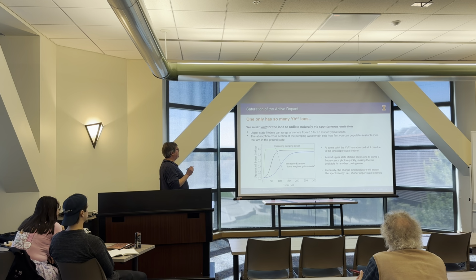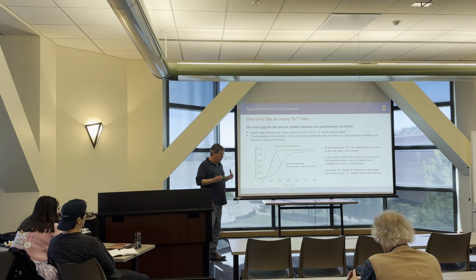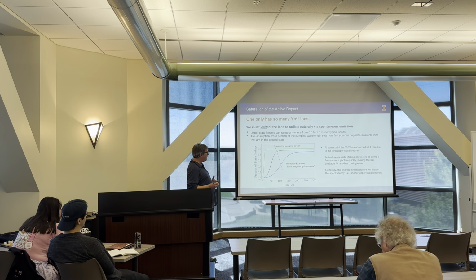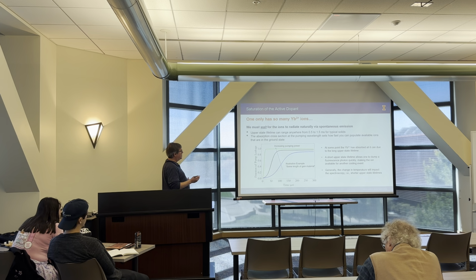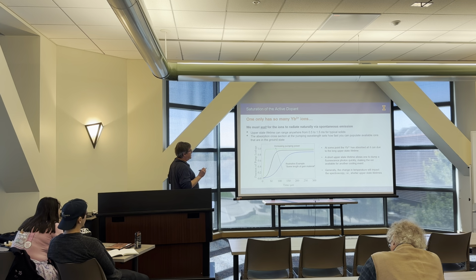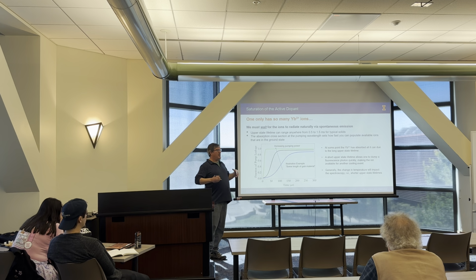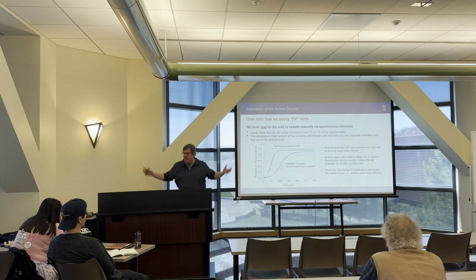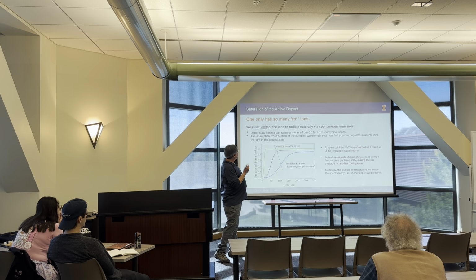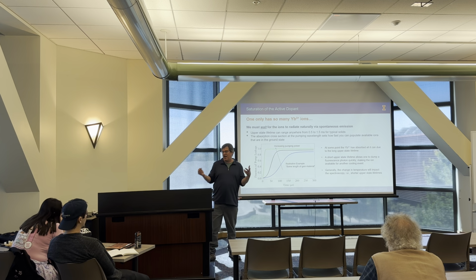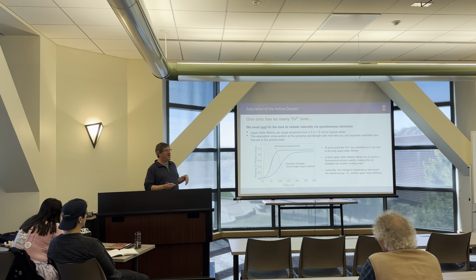Anyway, the upper state lifetime tells us how fast we can cool something, how fast we can extract photons from the system, and thereby thermal energy from the material. But the absorption cross section at the pumping wavelength also sets how fast you can populate the upper state. The larger the absorption cross section, the faster you can populate the upper state. It just turns out that for many materials, the product of the cross section and the lifetime is about constant.